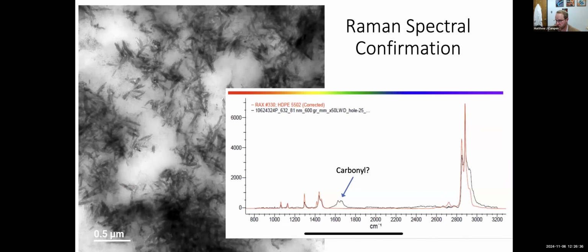it's plastic. This is a Raman spectroscopy, and you can see that the peaks that we see in black are the plastic particles, and comparing that to a library standard of high density polyethylene, there's a lot of overlap there, minus this peak around 1600 to 1700, which is very commonly associated with the oxidative formation of carbonyls on polymers.